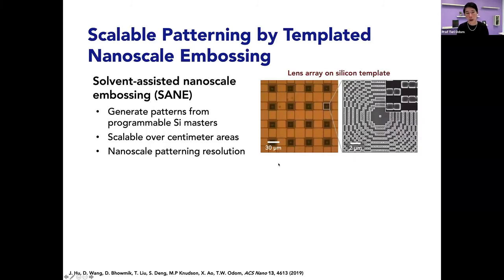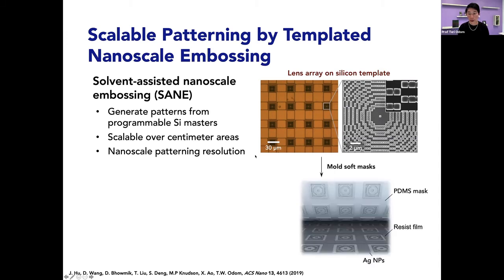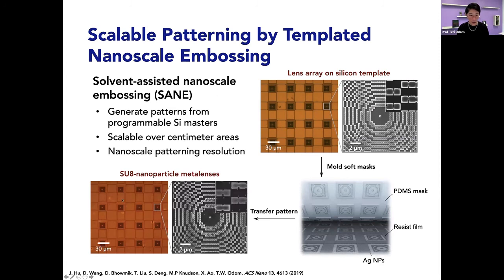But we were interested in the scalability of these structures. So what we wanted to do is to reconfigure arrays of lenses all at the same time. So we use this approach called solvent-assisted nanoscale embossing. We start off with these lens arrays in silicon. We mold these soft masks, which will transfer this pattern onto the lattice. And then this is what we get in terms of these SU8 patches.